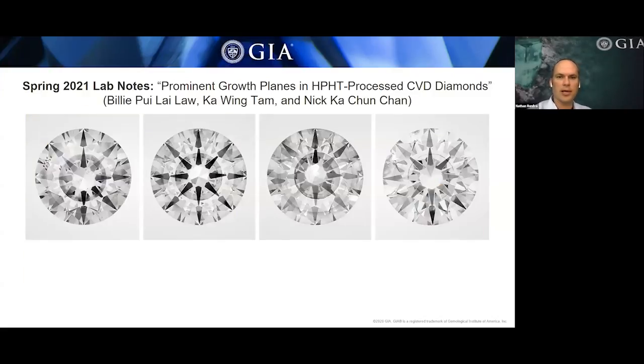There's also a lab note on 4 CVD diamonds that had prominent growth planes. And these CVD diamonds were also HPHT processed. And what you see in the diamonds are these concentric rings, or this bullseye effect. And this is a result of the layered growth from the CVD process.